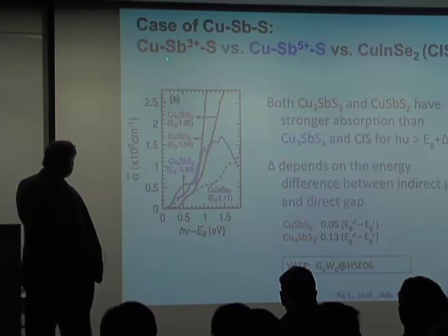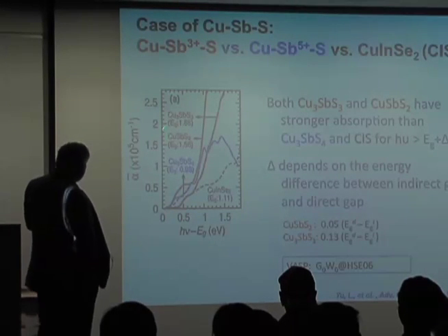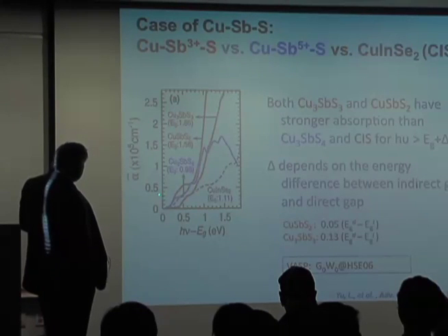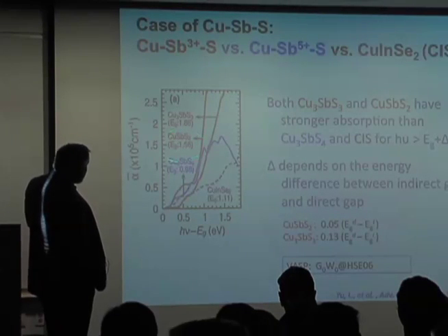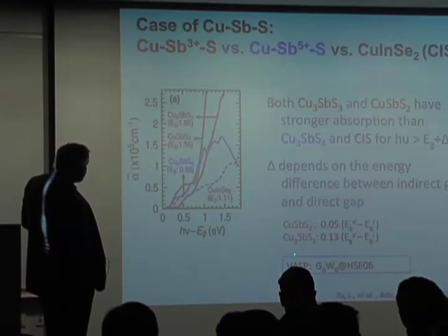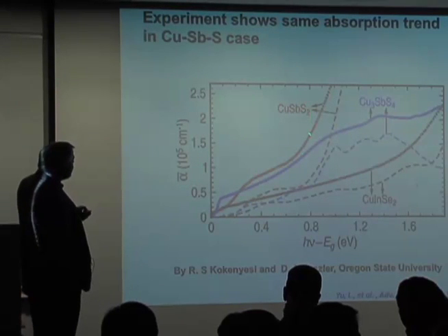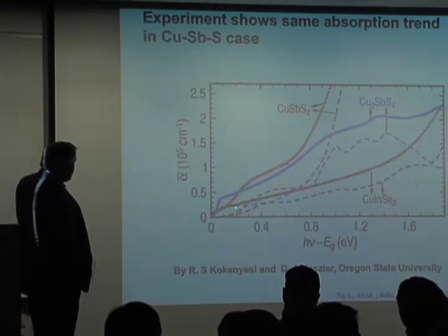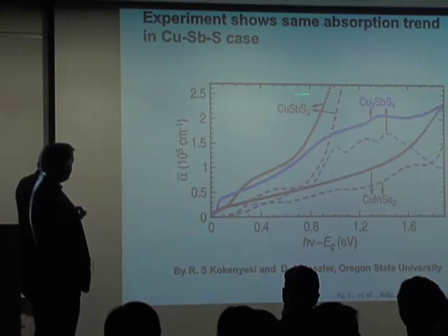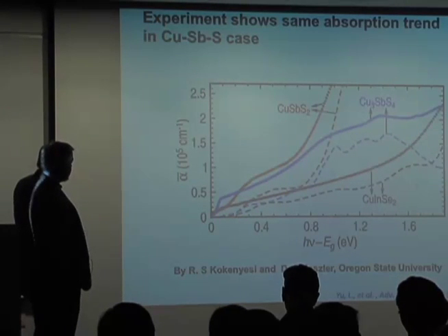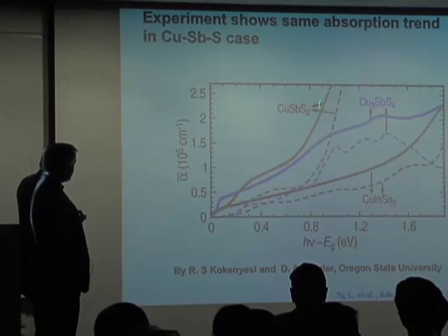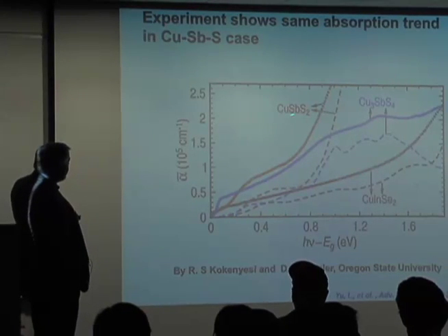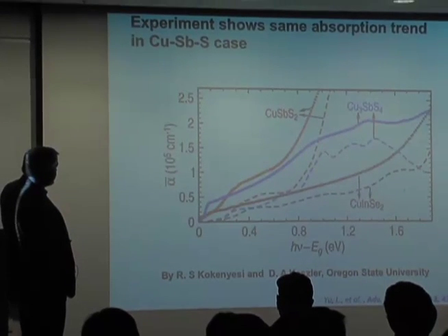And when we do that, and here's a case of just antimony 3 versus antimony 5, 2 compounds theoretically, what we see is that the lower valent antimony has a quicker onset and a much stronger absorption than the higher valent antimony. So then we actually can look at this system both theoretically, which is what the dotted lines are here, and we've actually looked at these now experimentally, and our folks at Oregon State have been able to show that these systems actually do have stronger absorptions for the lower valent system than for the higher valent system.